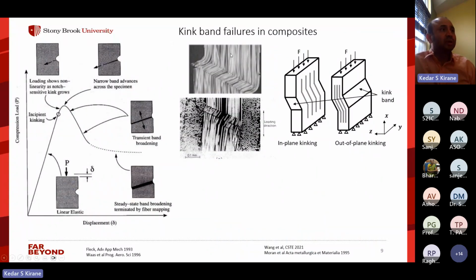So these kink band failures in composites happen because it's a two-scale, multi-scale phenomenon, and it is quite complex. Characterizing it and modeling it both are quite challenging. So what essentially happens, in the simplest terms, is fibers are very long and slender, and in the composite there is polymer around them, which holds everything together. But usually there is some kind of misalignment between the fiber direction and the loading direction. Because of this, locally somewhere the matrix gets damaged under shear. And when there is shear damage in the matrix, the fibers lose their support from the adjacent polymer. And this enables a micro-buckling type instability in these fibers.